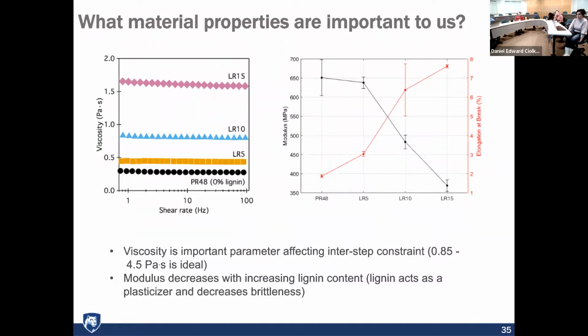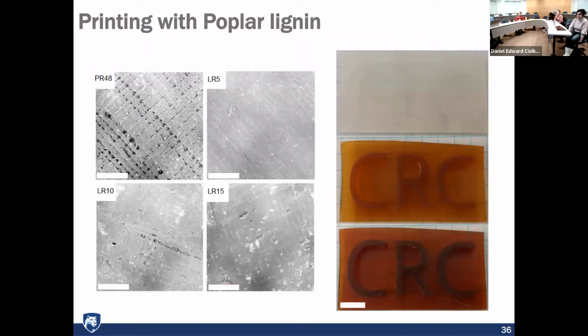And then we can also test mechanical properties like viscosity of the resin, which I'll just mention. The viscosity is still low enough to work as a 3D printing resin. You can also measure modulus, which is a measure of the stiffness. You can measure elongation, which is the measure of how ductile the material is. And all of these properties improve as you add more lignin. And then I told you the surface resolution is really important. And so here you have electron micrographs of the surface. Here's the commercial resin. And as you add more lignin, you see that the surface is actually smoother. You get better resolution. You get better surface properties when you add lignin.